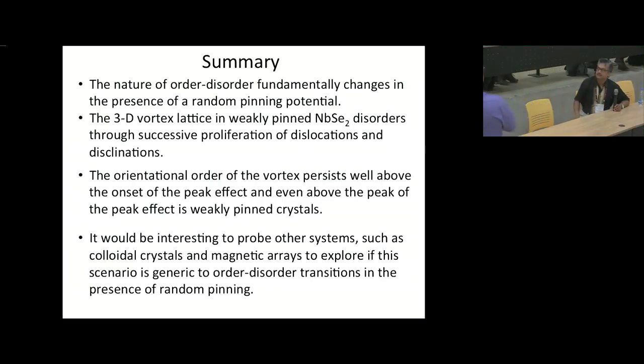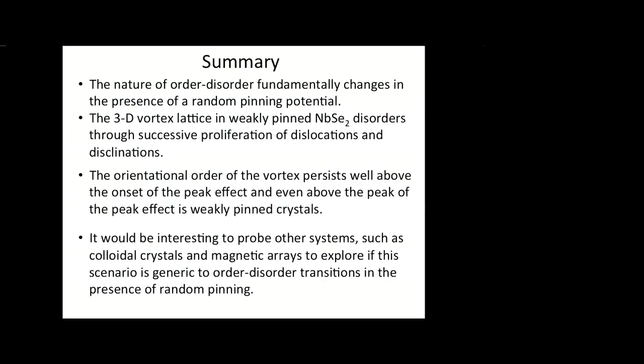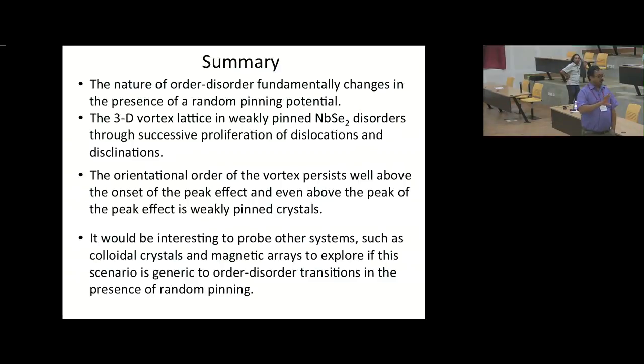Well, the system is not very strongly 2D. Structurally, though it has a layered structure, it's moderately 3D. So you don't have, let's say, pancake vortices like you have in high TC. The point is our imaging technique cannot look at the entire vortex. It looks only at the endpoints of the vortices.